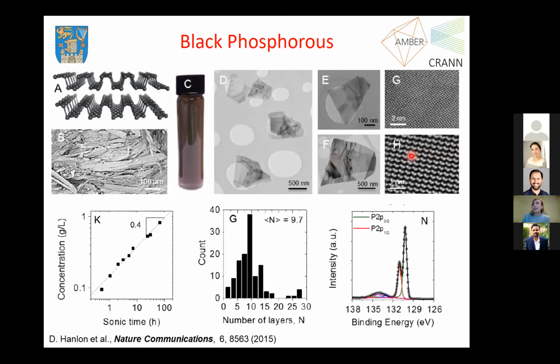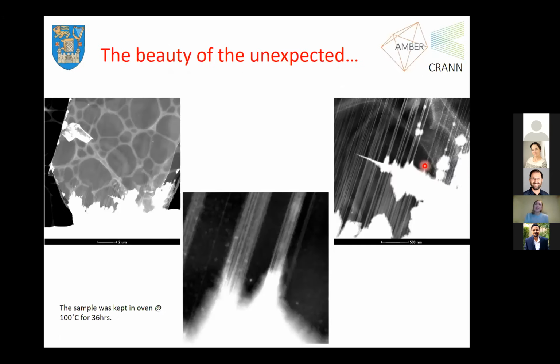So normally, to get this sort of images, you deposit the sample onto a TEM grid, and then we do a baking. Just shuffle it in an oven, temperature gradient, and we leave it there for a while. The unexpected was that we did the same with black phosphorus. We wanted to get atomic resolution imaging, especially of the edges. And what happened was that we left it there a few hours rather than a few minutes or half an hour, as we often do, because the solvent was quite thick and was not evaporating. So we decided to leave it there for a very, very long time.